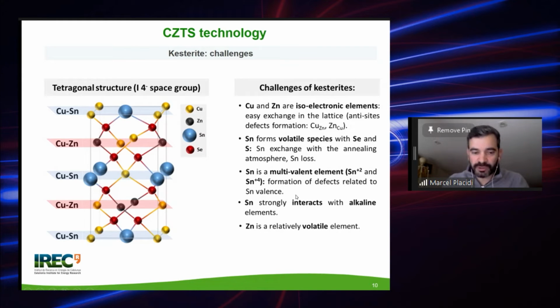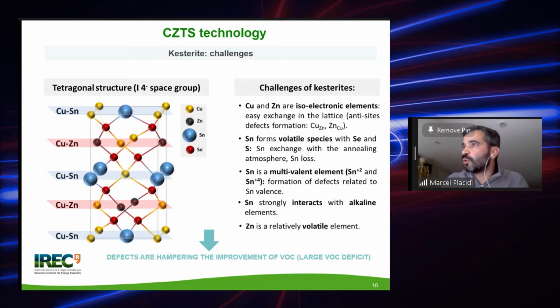Also, tin has a strong tendency to interact with the alkalis, and naturally, since in most cases this solar cell is directly grown on a glass substrate, glass contains alkali, and it could contain sodium in particular, and sodium can be problematic if we don't control the quantity. Okay, zinc is also a relatively volatile element. So all these defects that can be formed are more or less the main reason why the efficiency is not increasing so much until now, and explaining the VOC deficit.